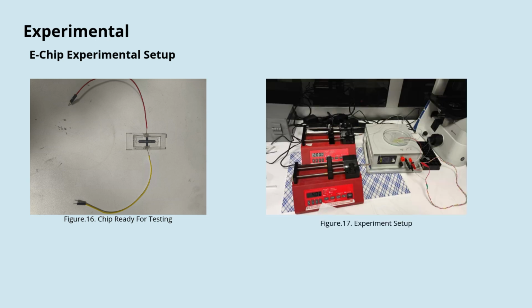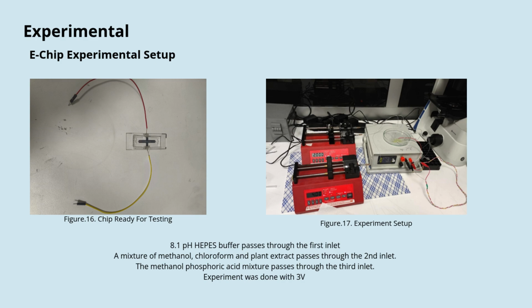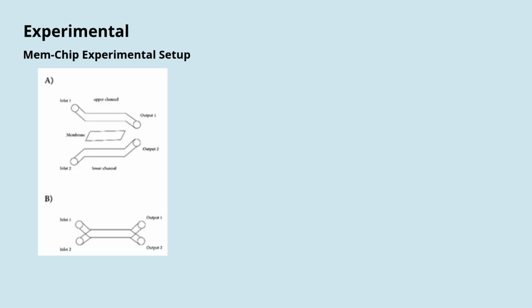The E-chip was tested by introducing three fluids through its three inlets. 8.1 pH buffer from the first inlet, a solution of methanol, chloroform, and plant extract from the second inlet, a phosphoric acid mixture from the third inlet. A voltage of 3 volts was applied. Samples were collected from each outlet separately and they are labeled accordingly.